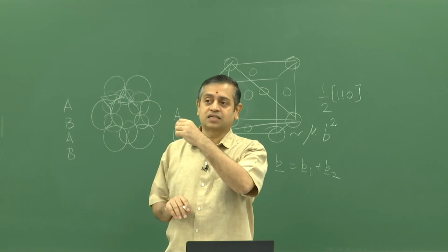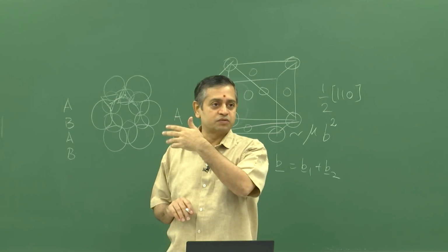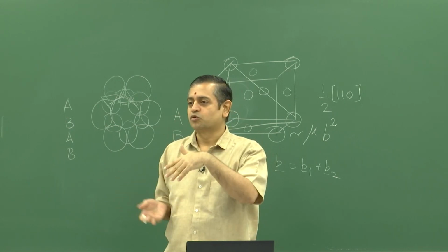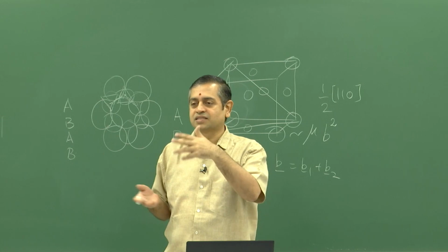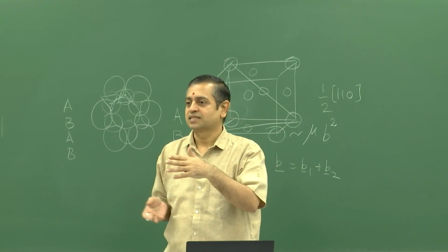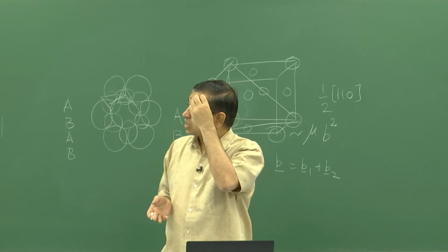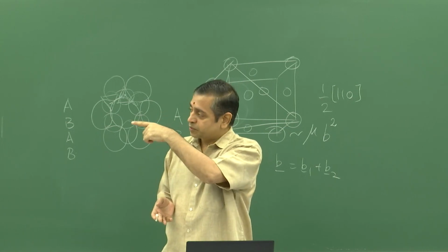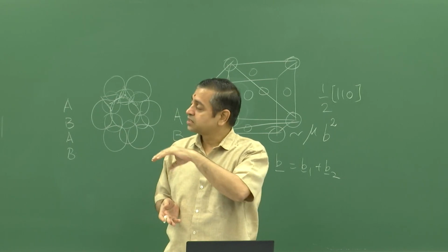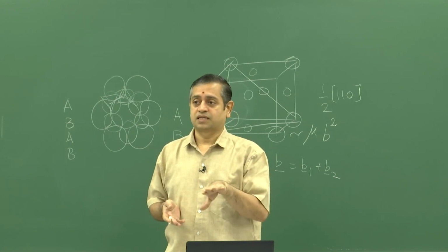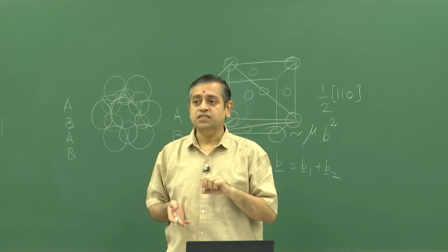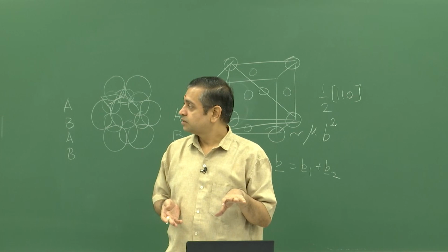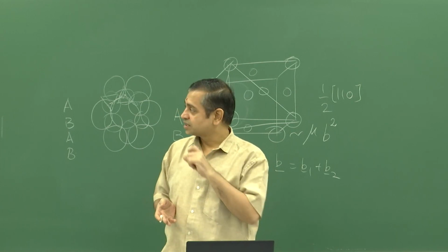And very high stacking fault energy materials obviously do not twin, because the stacking fault is costly, and you can think of one twin boundary energy as about two times the stacking fault energy or something like that. So it is costly and it does not happen. So, there is an intermediate regime where you see predominantly twinning, and especially in these intermediate stacking fault energy materials, experimentally you will see twinning at low temperatures and high strain rates. That is a combination which will lead to twinning. Remember this, because this is important for us later.